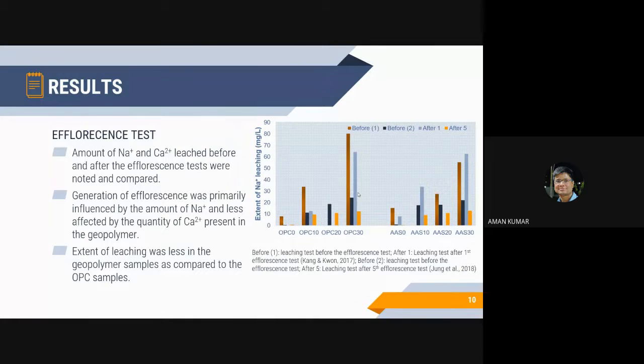Leaching tests were conducted before and after the efflorescence test to understand the mechanism of the formation of efflorescence. It was observed that the primary cause of efflorescence in the red mud containing sample was due to the amount of sodium ion present in it, although the extent of leaching was less in the geopolymer samples as compared to the samples prepared using Portland cement.